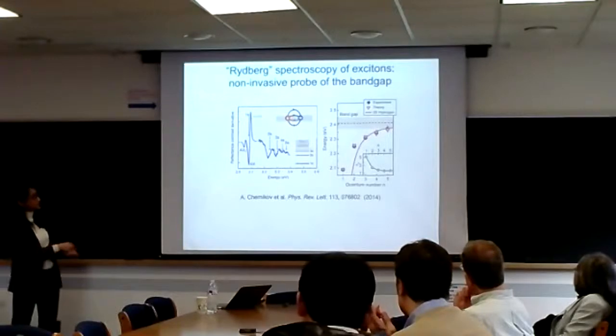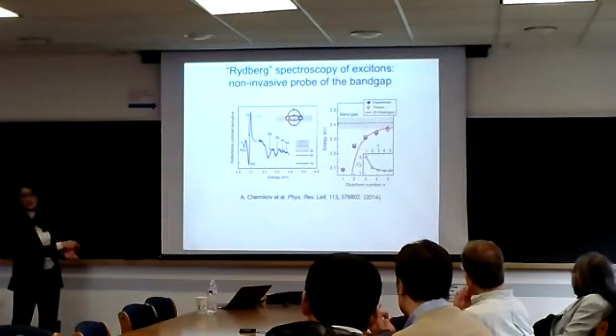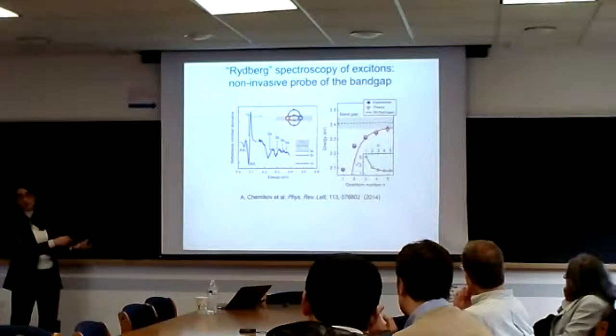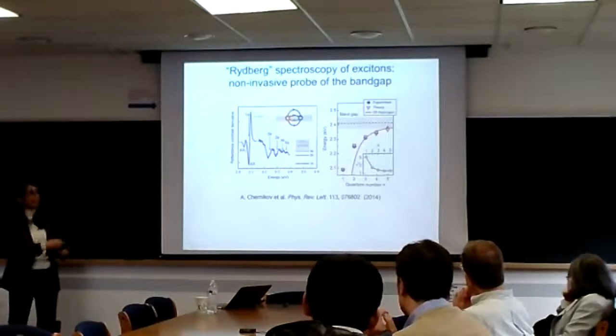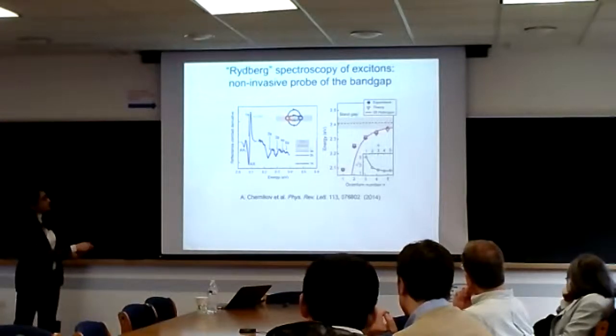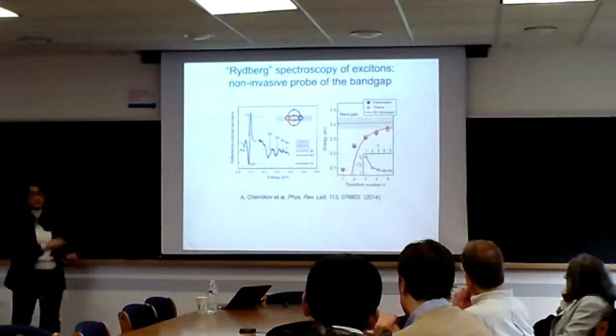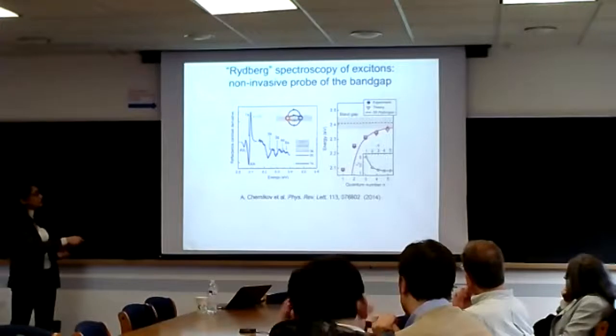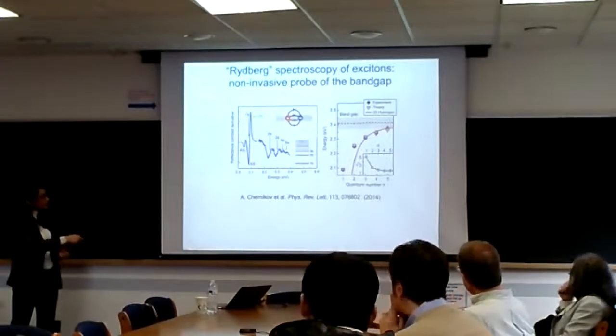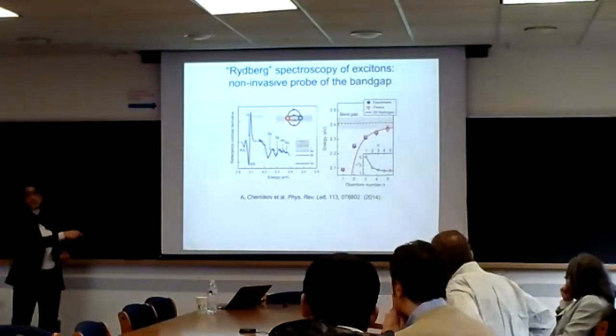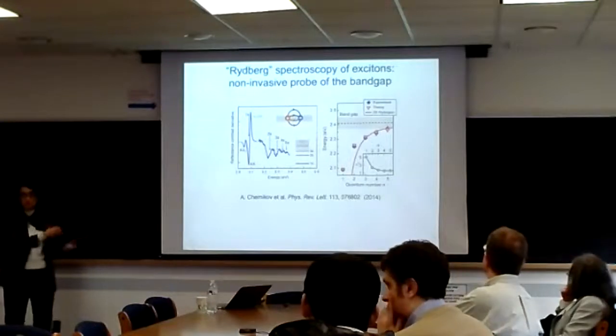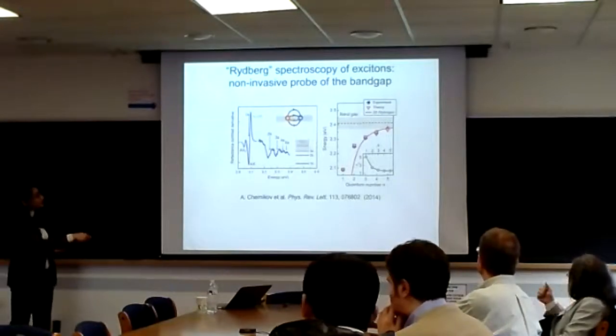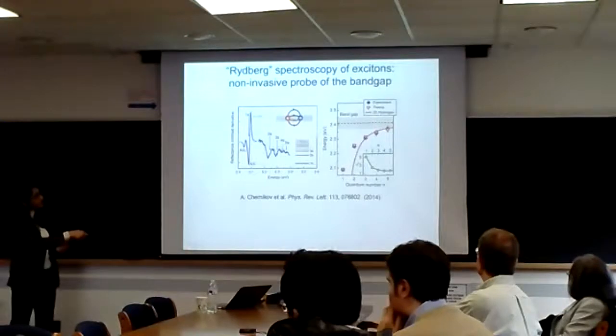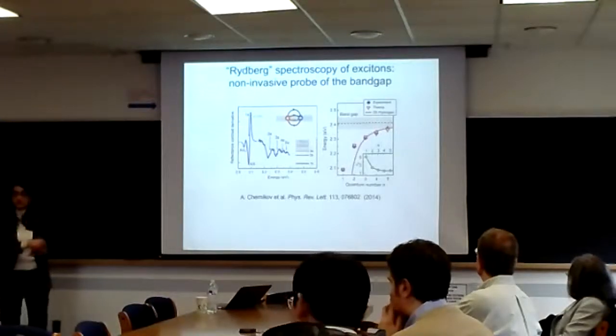So obviously the 2D hydrogen does not fit for this lower state number. So it's ad hoc. Here, what they've done is showing just the screening that they use for the lower state versus the higher state, and this changes. So you're right that this approximation is not correct at this limit, but as it becomes larger and larger, it becomes more appropriate. That's what the red line, which is the 2D hydrogen, shows, and this theory is not that. Yeah, I know what this is. Right.